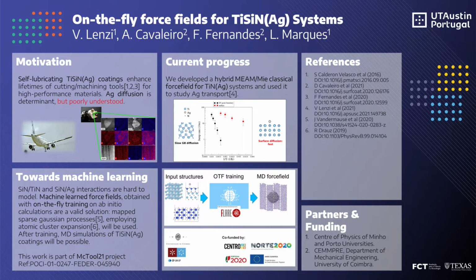Unfortunately, this atomistic model cannot be expanded in order to include silicon nitride, because the interaction between titanium and silicon and between silicon and silver is hard to model. In this research, we plan to use machine learning techniques to solve this problem and to obtain an atomistic model capable of dealing with titanium, silicon nitride and silver systems at the same time.